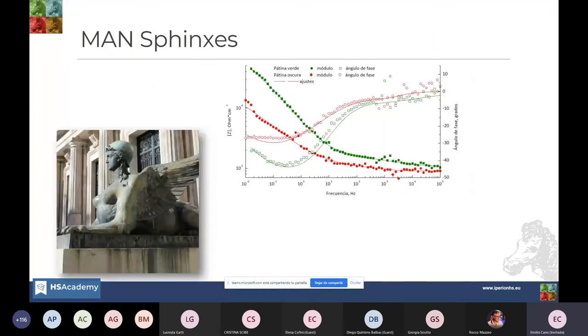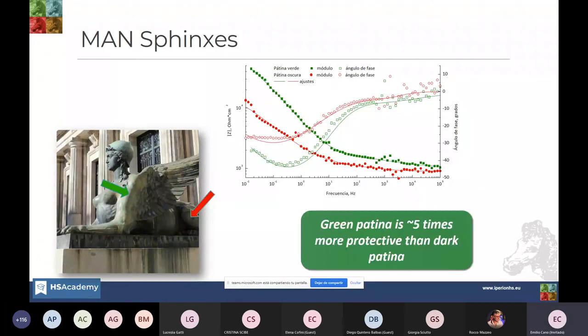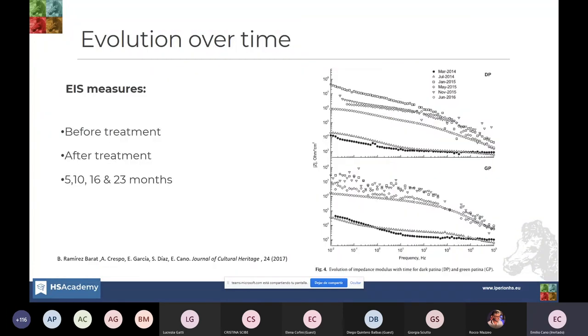And using this in two different areas of the Sphinx, we have been able to compare, for instance, the performance of the patina in the arm. The green patina is about 5 times more protective than the dark patina in the leg. But what is even more important, we have been able to measure the performance of this coating over time. So we measured that before treatment, before restoration. You see in the dark dots in the diagram, and you see how after the application of the treatment it goes up,